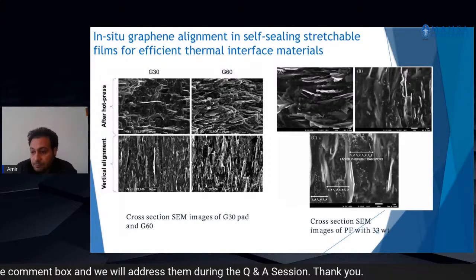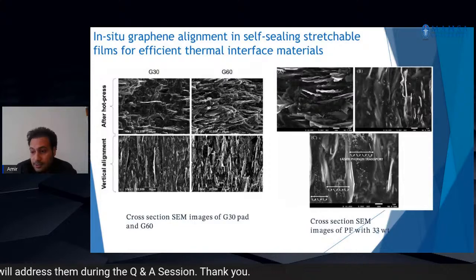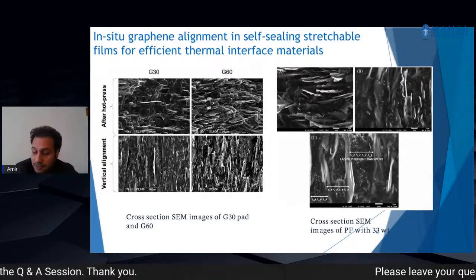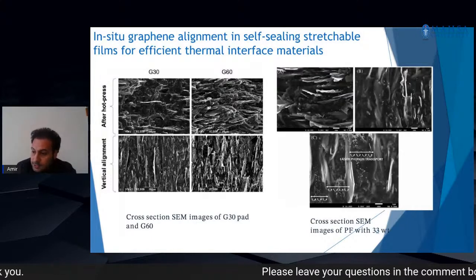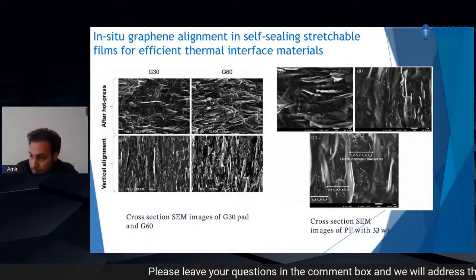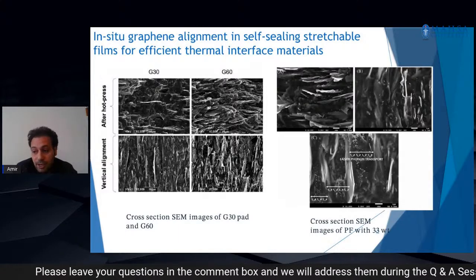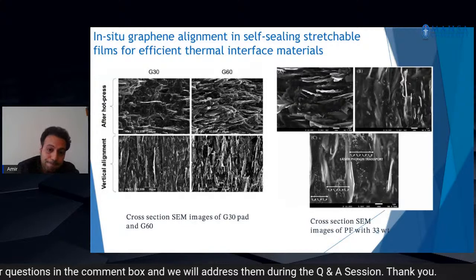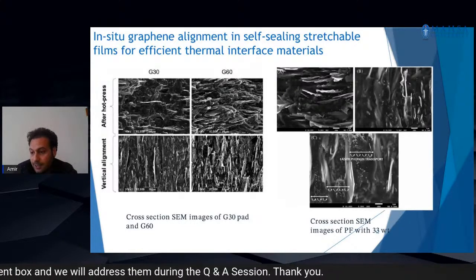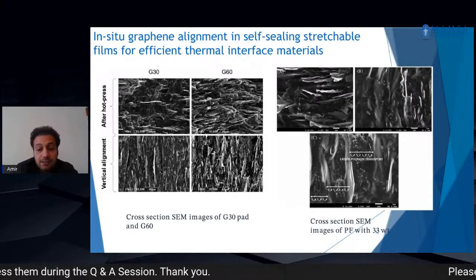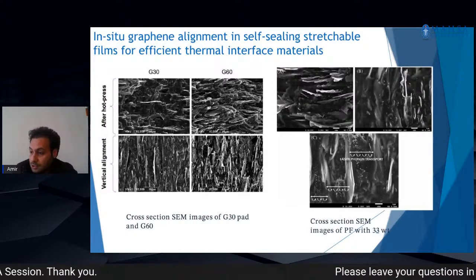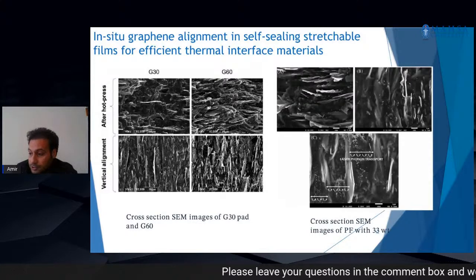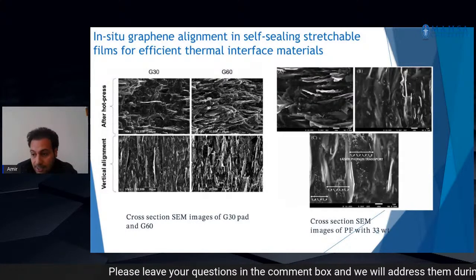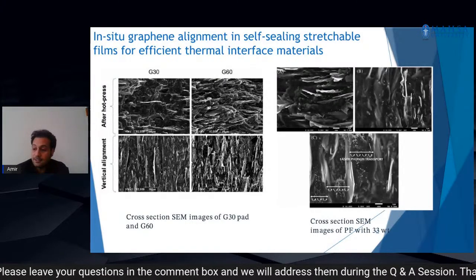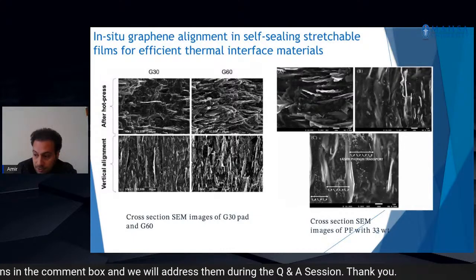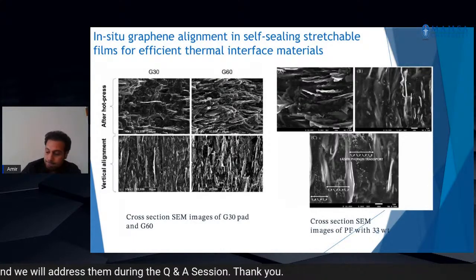Similarly, for the hybrid system with the MWCNTs, after the process with hot compression molding, the GMPs were also aligned with the multi-wall carbon nanotubes network that is clear in the bottom image on the right side. So the horizontal and vertical MWCNTs appear, and they are always aligned with the basal plane of the GMPs in our samples.